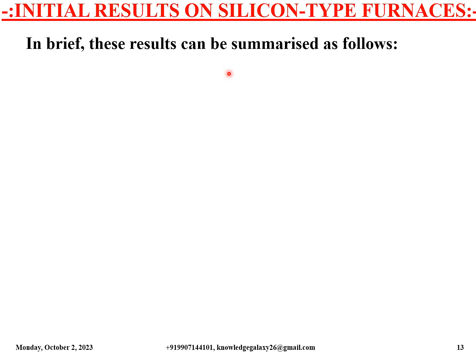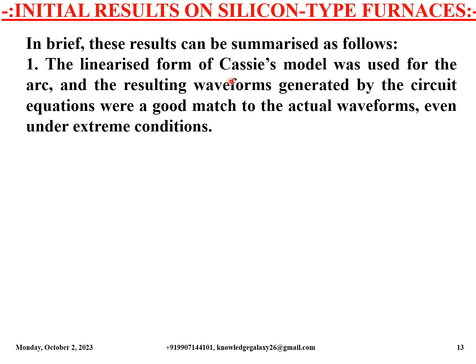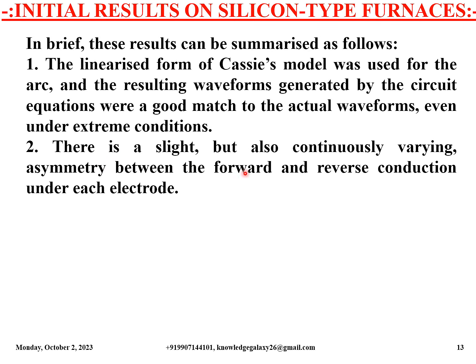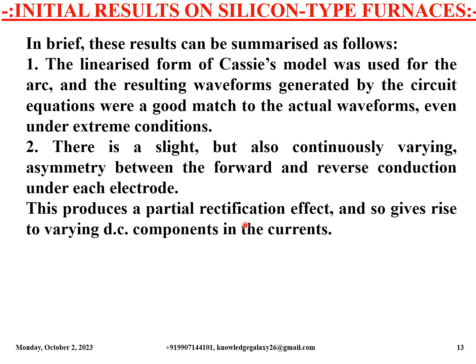In brief, these results can be summarized as follows. First, the linearized form of Cassie's model was used for the arc, and the resulting waveforms generated by the circuit equations were a good match to the actual waveforms even under extreme conditions. Second, there is a slight but also continuously varying asymmetry between the forward and reverse conduction under each electrode. This produces a partial rectification effect and so gives rise to varying DC components in the currents.